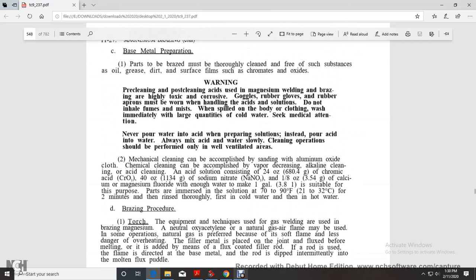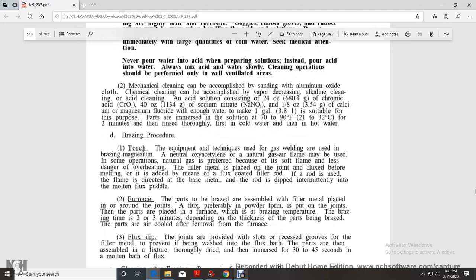Mechanical cleaning is accomplished by sanding with aluminum oxide cloth. Chemical cleaning is accomplished with vapor degreasing, alkaline cleaning, and an acid solution consisting of 24 ounces of chromic acid, 40 ounces of sodium nitrate, and 1/8 of an ounce of calcium or magnesium fluoride within water, made up to 1 gallon. It is suitable for this purpose. Parts are immersed in the solution at 70 to 90 degrees Fahrenheit for 2 minutes, then rinsed thoroughly, first with cold water, then in hot water.